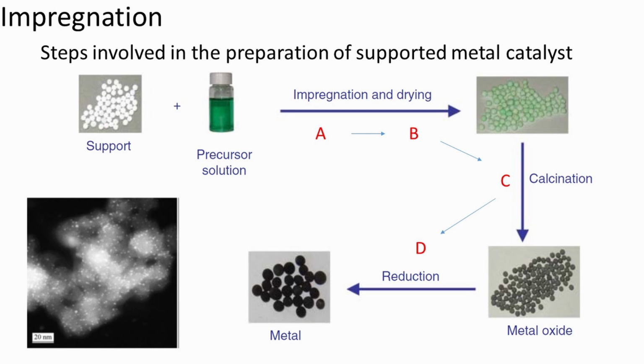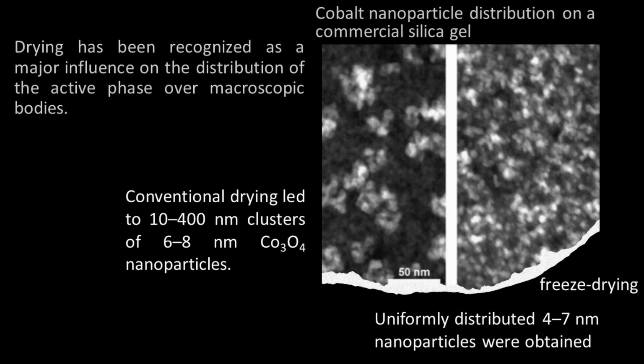If strong interaction between the precursor species in solvent and the support prevails, it is expected that the distribution over the support will not change much upon drying. In case the interactions are weak, extensive redistribution may occur. In addition, if the drying process is not carried out carefully, the catalytically active materials may become concentrated at the mouth of the pores, or may even move onto the outer surface of the support.